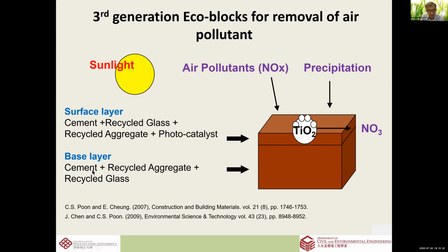Okay, base layer, we try to use as much recycled material as possible. Recycled glass and recycled aggregate provide the mechanical properties, and the strength of this is up to 60 megapascal. This is suitable for use in pavement for vehicular access, and the recycled material content is up to 50 to 60%, and this provides the strength.